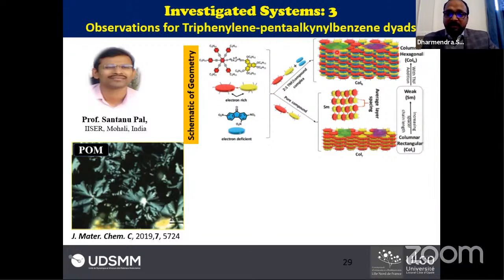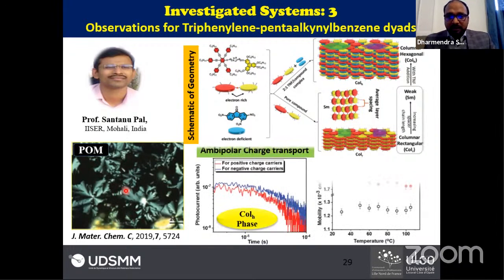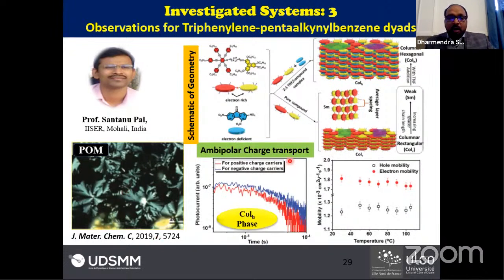So he doped this system into different systems, and he found the hexagonal columnar, hexagonal columnar rectangular as well, and intermediate symmetric phases as well. So he proved that yes, this compound shows mesomorphic properties, and we did the charge transport properties for him. Obviously, due to the heavy bulky nature, we obtained a dispersive curve in the charge transport, but we obtained ambipolar charge transport for these compounds, in which electron mobility and hole mobility are almost temperature invariant, but electron mobility is higher in this compound, though the difference is not so prominent.